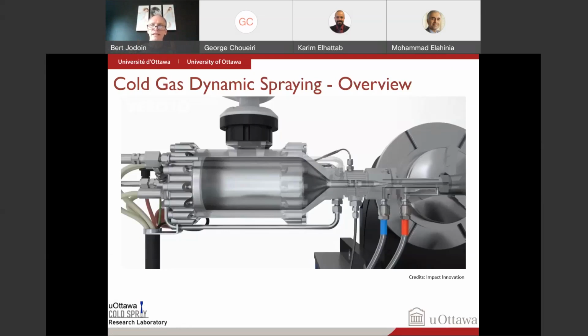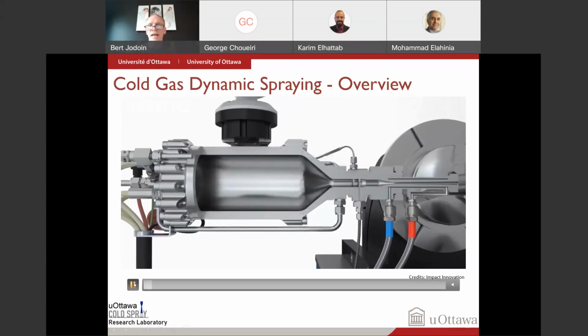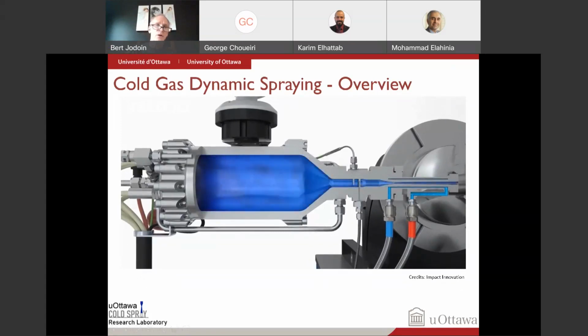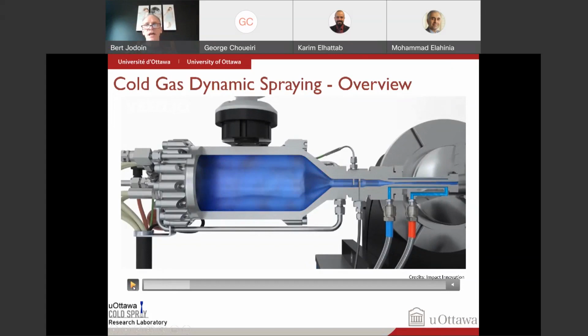We're using this setup right here, which is a cold spray gun. So you can see here what you have is a converging, diverging nozzle in this part. So this is pretty much what a rocket engine is. It's a converging, diverging nozzle. So as you know, if you inject a gas, in our case, it's mostly nitrogen, we're going to introduce nitrogen in this setup. The gas will accelerate through the converging, diverging nozzle because you convert thermal energy into kinetic energy and you get a supersonic flow in this zone here at high speed, which reaches about 2,000, 3,000 meters per second, depending on the spray parameter you're using.